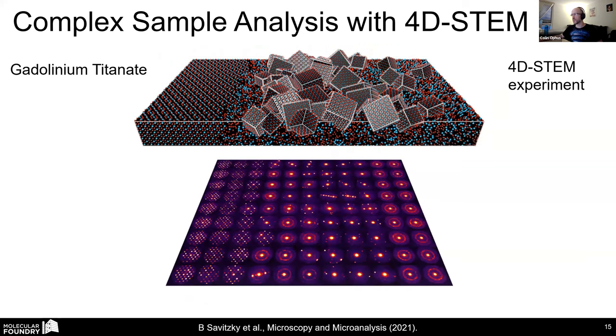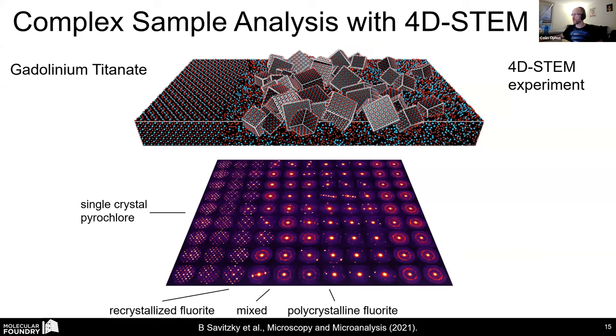So once again, if you look at the sort of tableau of this, you have single crystal pyrochlore, recrystallized fluorite, a sort of mixed amorphous and polycrystalline fluorite region, a mixed area, and then at the surface of the film, this fully amorphized zone here. So this is about a micrometer field of view here, square, give or take. And this is why this technique is gaining favor in material science for problems like this, because we can scan arbitrarily large fields of view and still get atomic scale information.